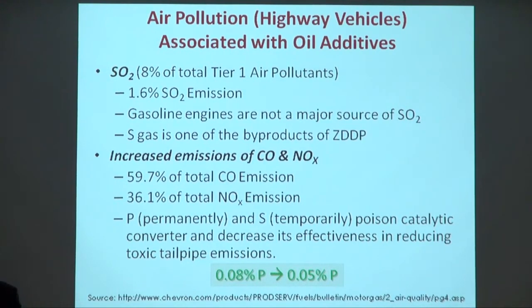So one of the challenges that I will try to address here is, what if we try to take a gradual step in the right direction, which appears to be huge for the oil industry, to reduce some of these important elements that have made some of these additives the prime additives that this industry has been using for more than 40 or 50 years. In particular, phosphorus, to reduce it by about half in terms of its content. You may be surprised that these numbers are very small, but additives represent a very, very small fraction of the content of oils, but nevertheless their effect is far-reaching.